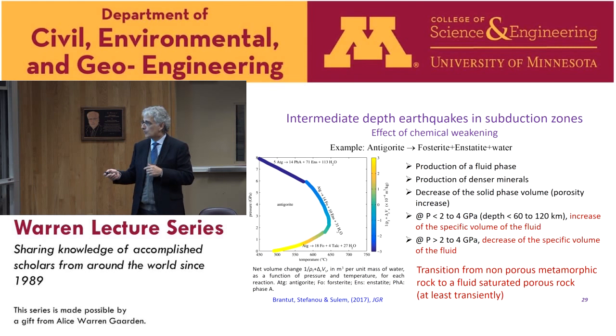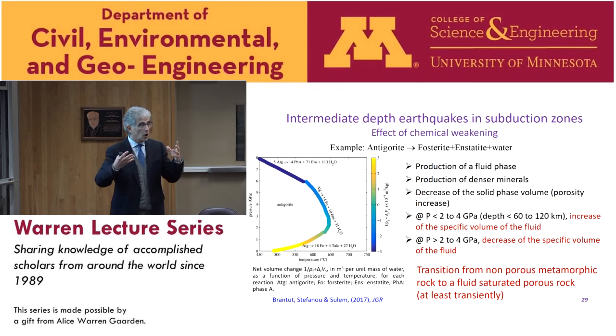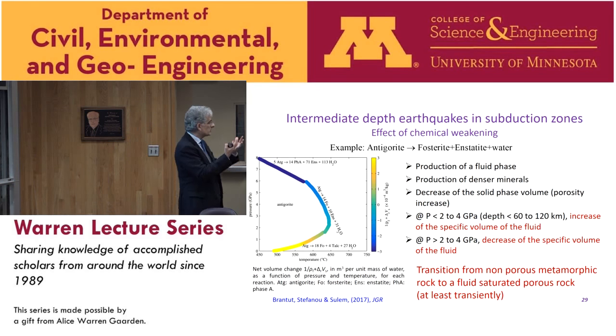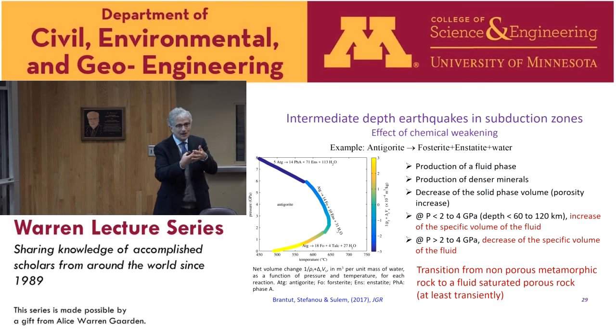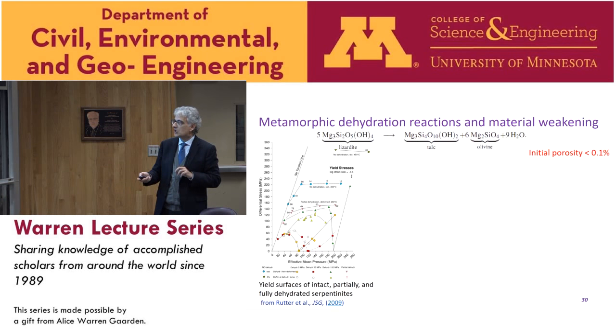We have the transition from a non-porous metamorphic rock to a fluid-saturated porous rock under an increasing effective stress, and this causes pore collapse, and thus, as a secondary effect, an increase of the pore pressure, and then brings the state of stress back again in the brittle regime. So in the two cases, for different reasons, we have this dehydration embrittlement. So I would like just to show one example of modeling for this particular case that we have derived in a recent paper in JGR.